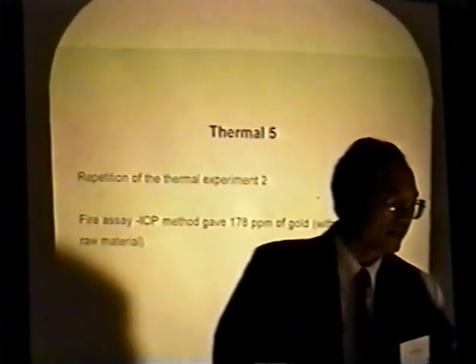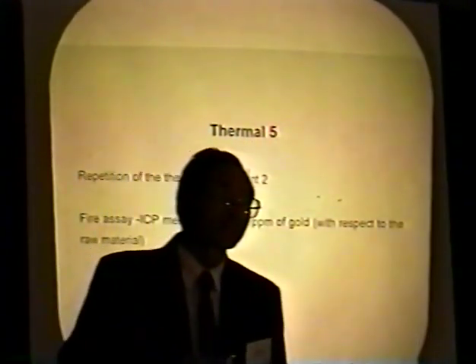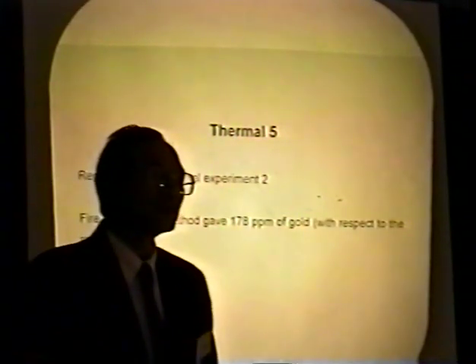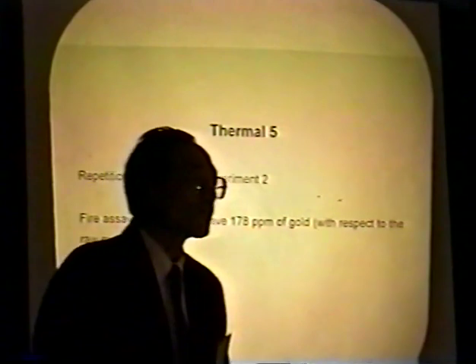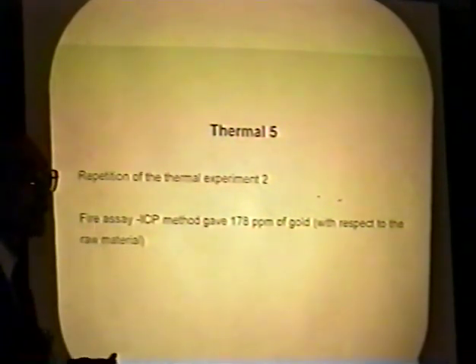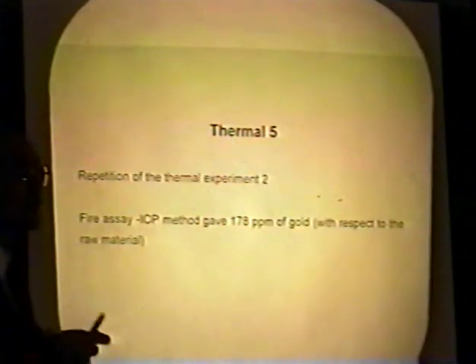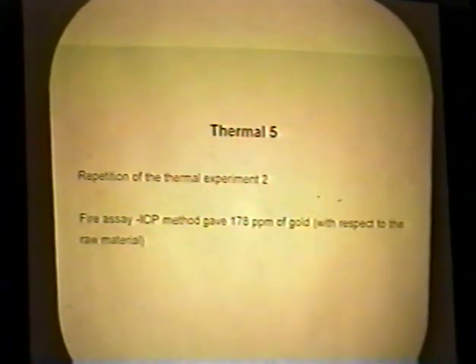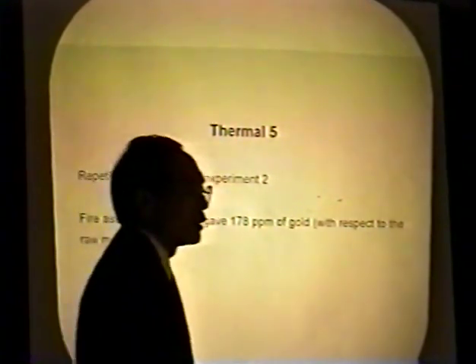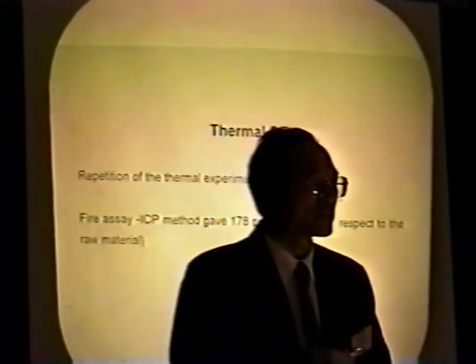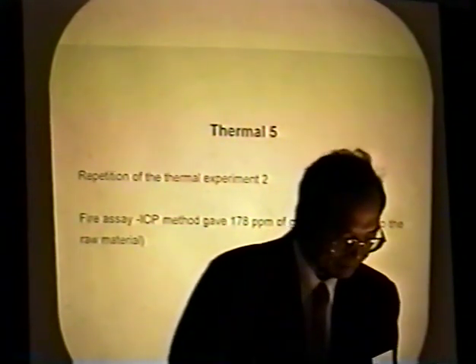Next experiment, we wanted to duplicate it, so we made Thermal 5. Thermal 5's composition is the same as Thermal 2 - not sand, but pure chemical, without nickel, without plating, we add CaO for Thermal 5. Thermal 5 is exactly the same as Thermal 2, just duplicated. Using ICP method, we got 178 ppm of gold. That's with respect to the raw material, including all the silicon oxide, whatever, carbon, everything included - 178 ppm.